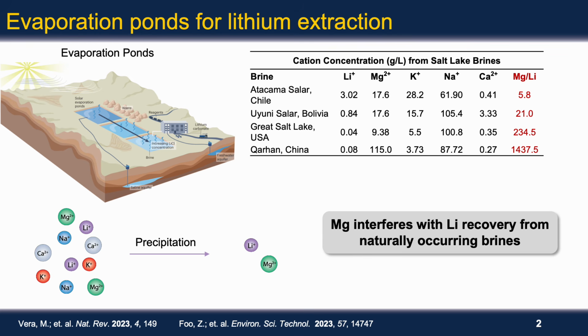The conventional process of lithium extraction from naturally occurring brines is evaporation ponds coupled with chemical precipitation. One of the main challenges of this approach is the significant amounts of magnesium ions in these brines, oftentimes at much higher concentrations than lithium, and this complicates the separation due to the chemical similarity of lithium and magnesium. Essentially, lithium extraction from brines that contain magnesium to lithium ratios that are greater than 10 is unfeasible with the conventional approach. And so this has motivated an enormous amount of interest in lithium-magnesium separations, particularly using membrane-based technologies.